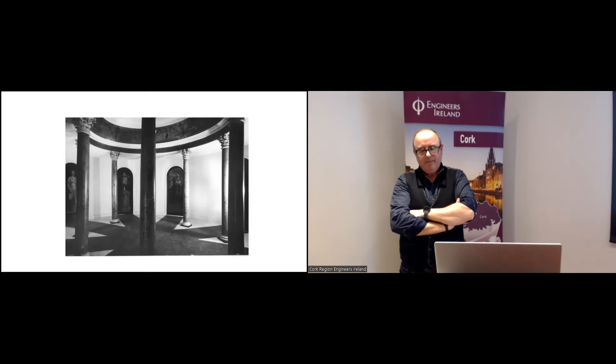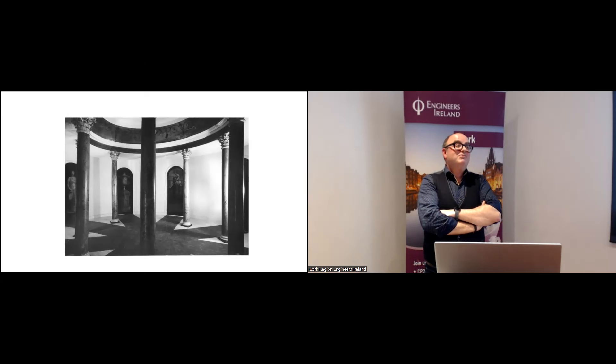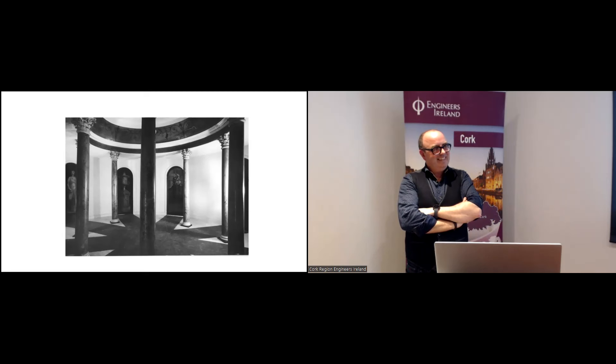Eamon asks: do you have a record of the number of man-hours it took to build the rammed earth structure? We didn't keep a formal record, but for the lifts — approximately five metres — it was taking nearly 40 to 70 hours to come up 300 millimetres on a five-metre stretch. We were literally grading all of the earth with wheelbarrows. On a larger scale, you'd have machinery to grade the earth, a loader to load it into the form, pneumatic rammers — much more efficient. Alternatively, you manufacture it in a factory setting rather than the 'Egyptian method' we were using.